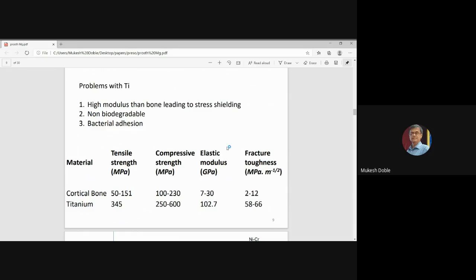So there is something called stress shielding that can happen. What is stress shielding? If some part of the load-bearing region has titanium, which has a very high modulus when compared to the bone, most of the load of the person will be transmitted through the titanium. So less load will be transmitted through the bone, and over a long period of time the bone will get porous. This is a very serious problem with metallic implants in load-bearing areas, because these will slowly become porous in nature. That is why a lot of research is being done